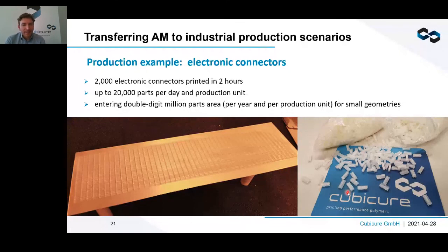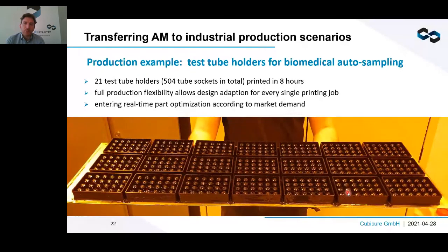And the second example shall remind you that in additive manufacturing we always also talk about part volume. If the parts become bigger, then obviously the throughput, the number of parts, goes down. That's inherent to additive manufacturing. But of course, with these large systems, you can also print a reasonable number of large parts in a very short period of time. For that example, we have a test tube holder where test tubes of the biomedical industry are placed, for example, for an auto sampling process. And here we see a full tray printed in 8 hours with these test tube holders. These holders are good to use with over 500 of these test tubes. So we're really talking about numbers.